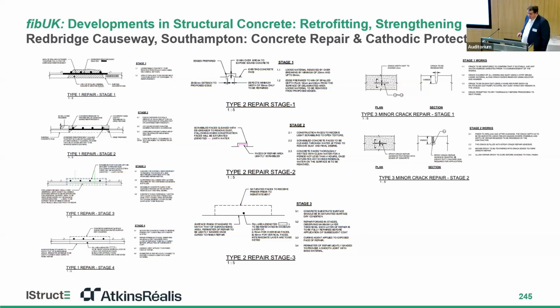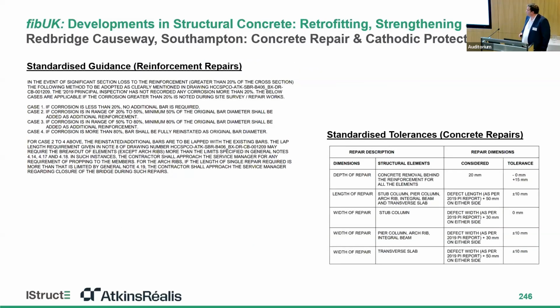So here's just an example of some of the repairs that we did. On the left-hand side was a standard repair to a spall where the reinforcement's exposed, a standard repair to a spall where no reinforcement is exposed, and a standard crack repair detail. So this enabled the contractor to make little adjustments on site in conjunction with the designer site representative, but you had a standard suite. You didn't need to keep coming back to us, and we weren't then the bottleneck for the works. The top left is an example of some of the reinforcement detailing rules that we gave them.